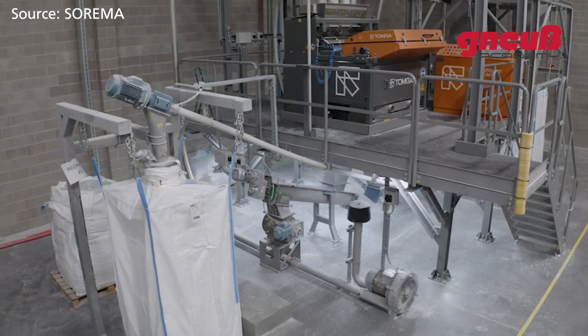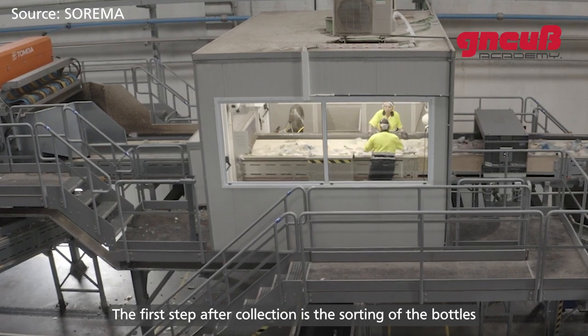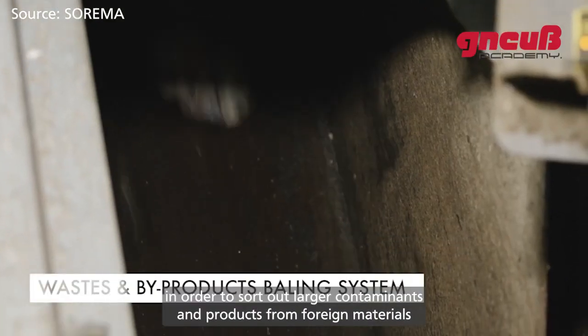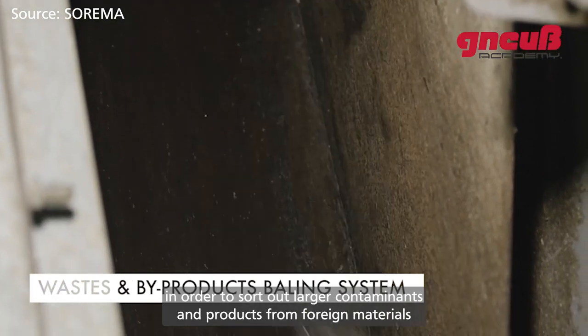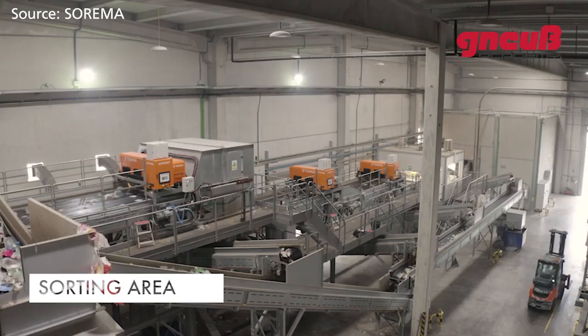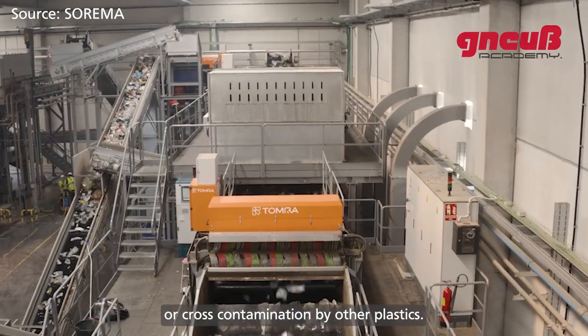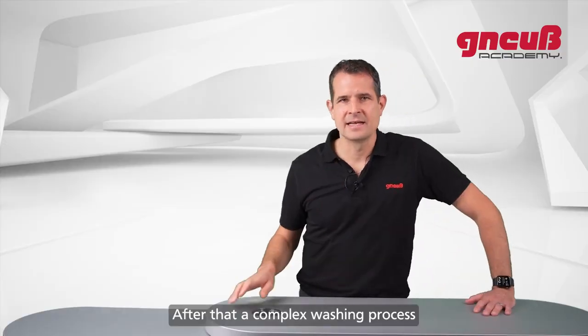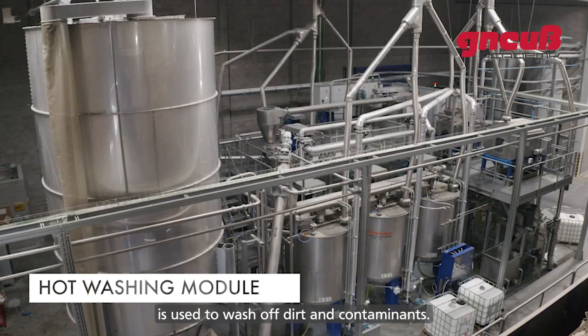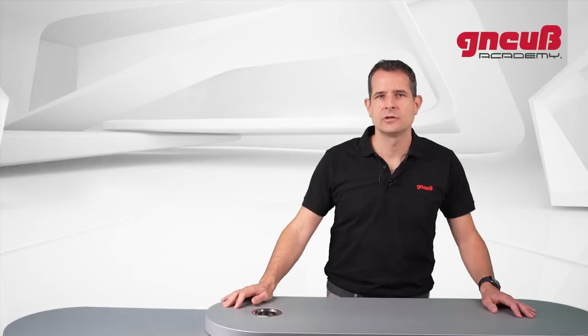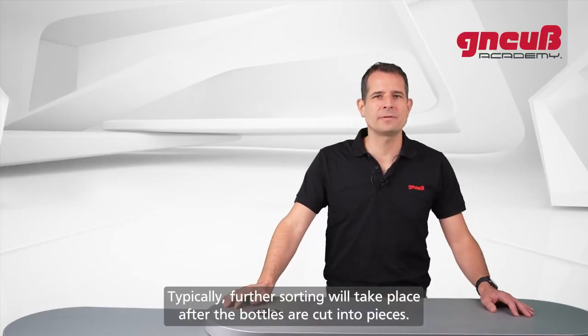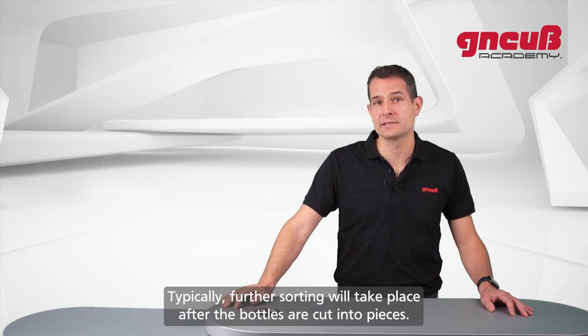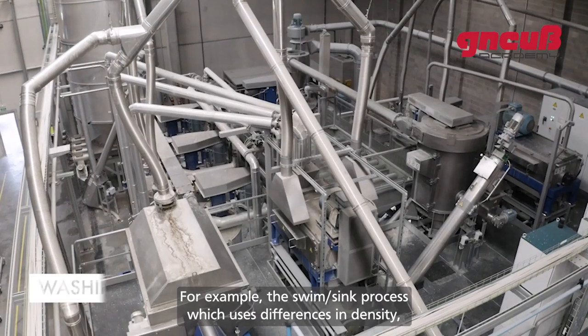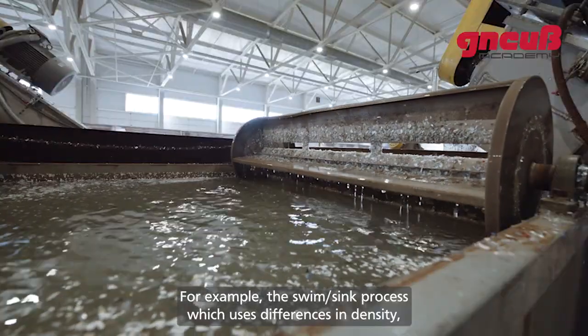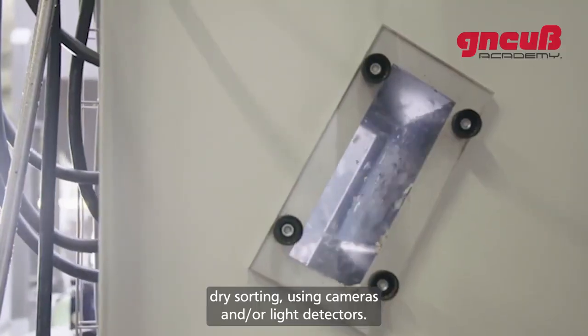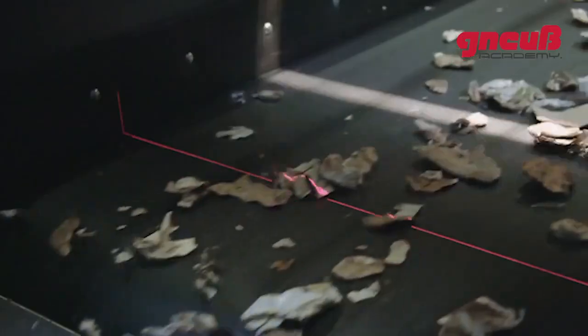The first step after collection is the sorting of the bottles in order to sort out larger contaminants and products from foreign materials or cross-contamination by other plastics. After that, a complex washing process is used to wash off dirt and contaminants. Typically, further sorting will take place after the bottles are cut into pieces. For example, the swim sink process, which uses differences in density, dry sorting using cameras and/or light detectors.